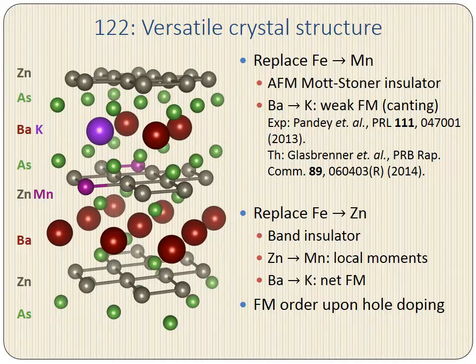In barium manganese arsenic, it is clear that this is due to a competition between superexchange and double exchange, and that this is what leads to the weak ferromagnetic canting. Now, in the case of barium zinc arsenic, it is less obvious what is going on, but in the end, we're going to conclude that the same mechanisms are again at play. The rest of this talk, then, is going to be dedicated to exploring the magnetic interactions in these systems and convincing you of these two basic points.